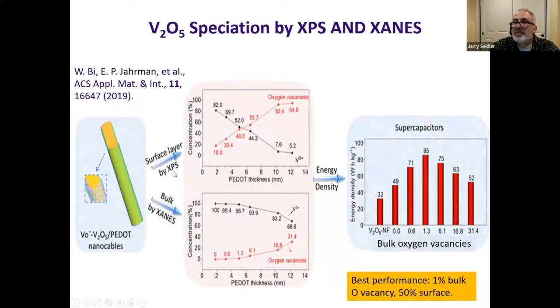Interestingly, whereas the XANES is bulk sensitive, the X-ray photoelectron spectroscopy, XPS, is only surface sensitive. The surface sensitive technique instead says the vanadium 4+ becomes extremely small by the time you're at this 12 nanometers of thickness. So clearly, this is a strongly surface-driven oxygen defect formation, which probably is not surprising given it's a surface coating method. But we were able to get at this idea that best performance involved some amount of bulk oxygen vacancy, sorry, I think that's 1%, and most of it being at the surface. I'd refer people to this paper for more details.